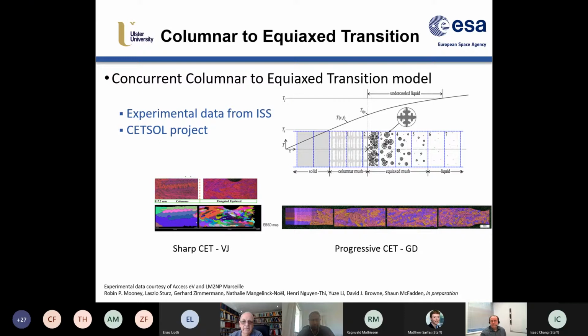Moving on to columnar to equiaxed transitions. So there's a series of experiments done throughout the CETSOL project. Experimental data was gathered from the International Space Station, where they did Bridgman type solidification. And under different kind of transient conditions, they were able to get different types of CET. And with a velocity jump, you get a very sharp CET. So you see this columnar solidification and then transitioning very abruptly into equiaxed.